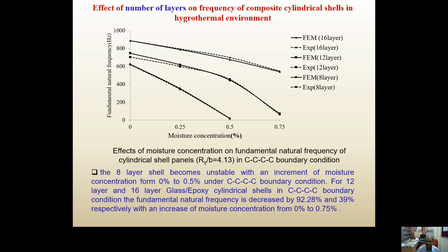Similarly, the effect of number of layers is studied also for the moisture concentration. With increase of moisture, the shell frequency has been found out for different layers. So at 0.5 moisture concentration, the 8-layer is negligible stiffness, but the 16-layer shows a very high stiffness, and significant stiffness is still retained, though everything is decreasing, with increase in number of layers.